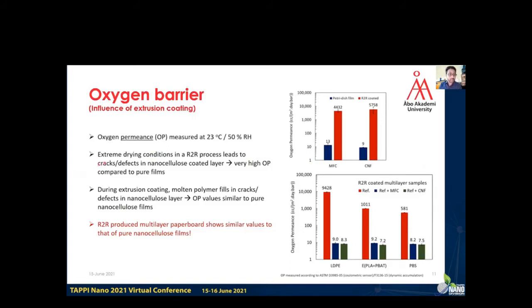This is probably due to the extreme drying conditions in the roll-to-roll process that lead to cracks or defects in the nanocellulose coated layer, and therefore a very high oxygen permeance compared to pure films. Also, the value for the films is for the same thickness, about 6 to 8 micrometers. If you have higher thickness nanocellulose films, they obviously have very low oxygen permeance, less than 10 or even 1 if you go up to 20 microns. But now moving to the figure on the bottom, interesting things start to happen.